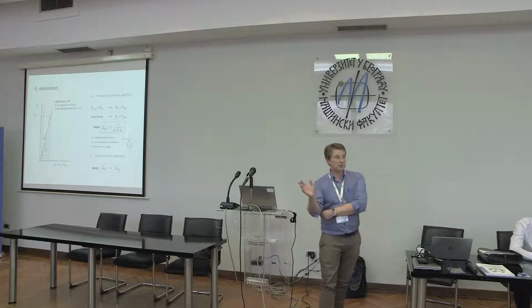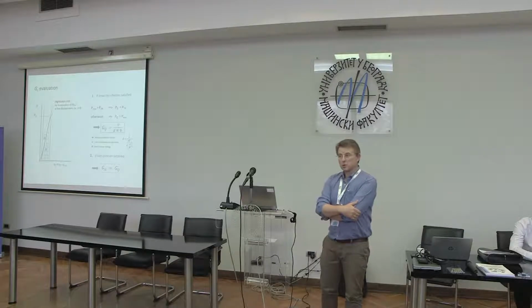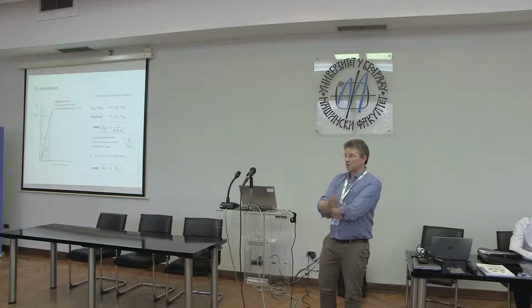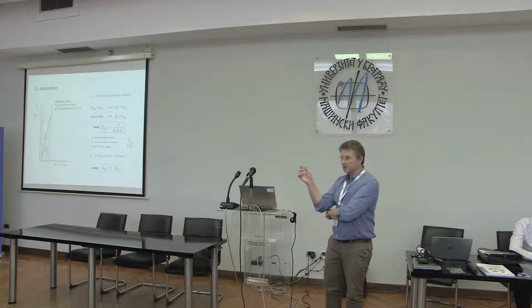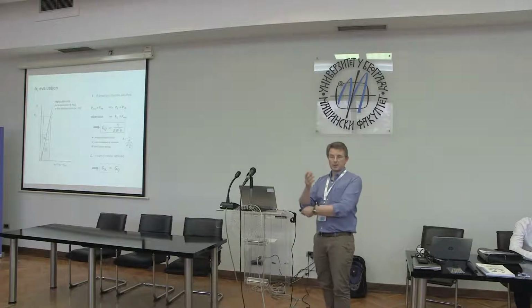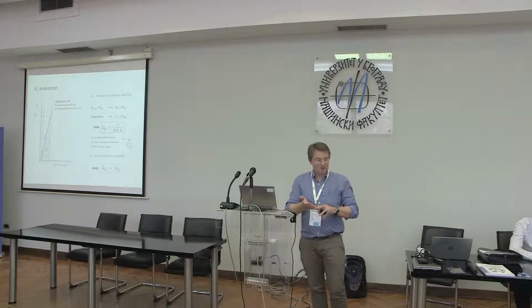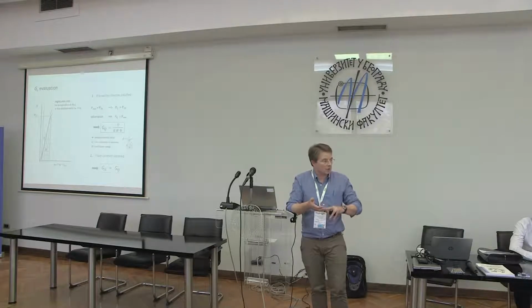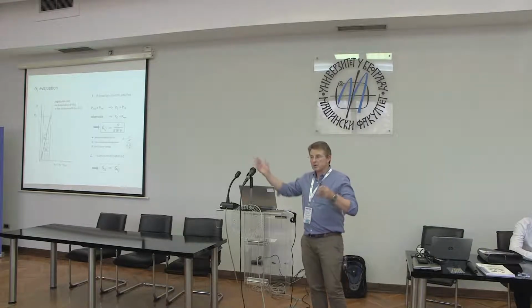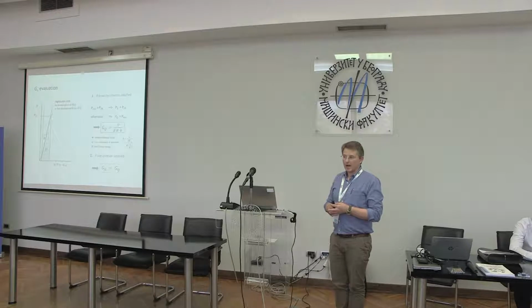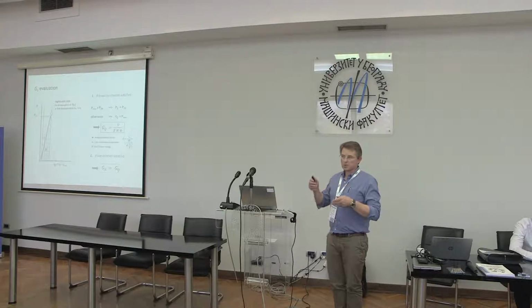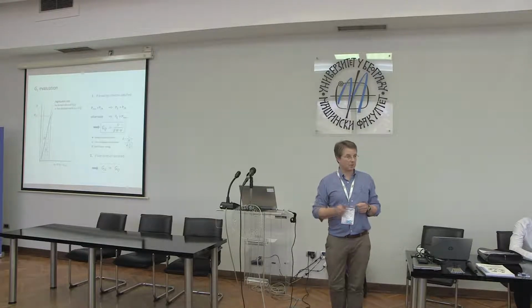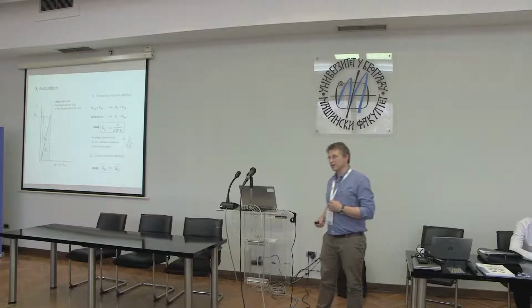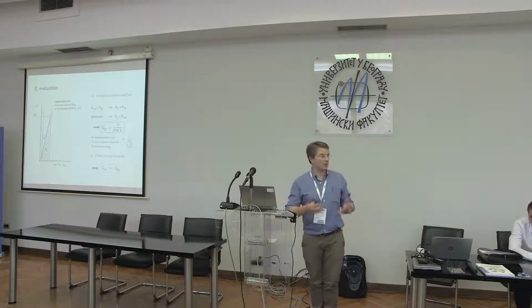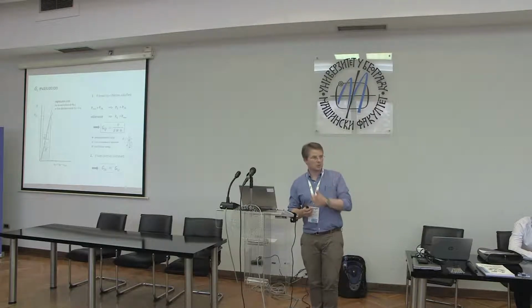In a multiple specimen approach, for example, you would try to achieve different levels of crack growth, and we're talking relatively small levels. So you might have a specimen where you load and try to achieve 0.1 millimetre of crack growth, 0.2, 0.3, up to maybe 2 or 3 millimetres. Our ability to precisely control that amount of crack growth and develop the JR technique is, at the moment for us, the limiting stage. We found it very difficult to get that complete control.